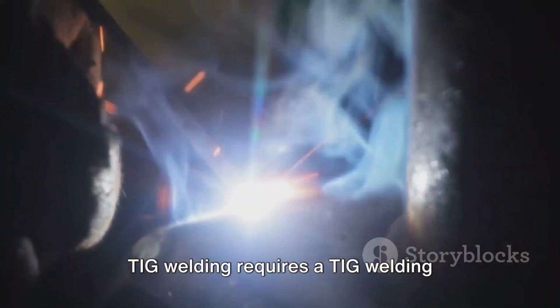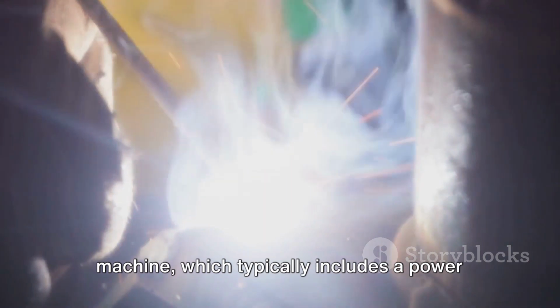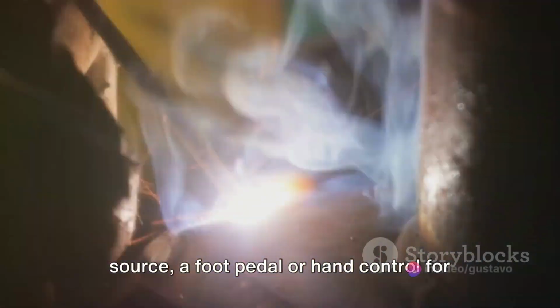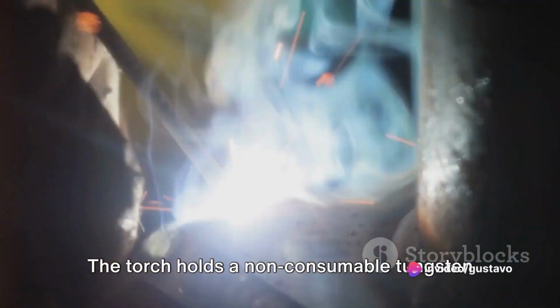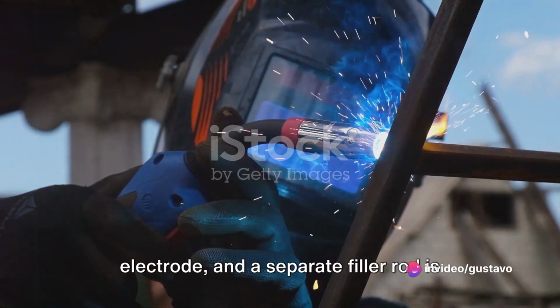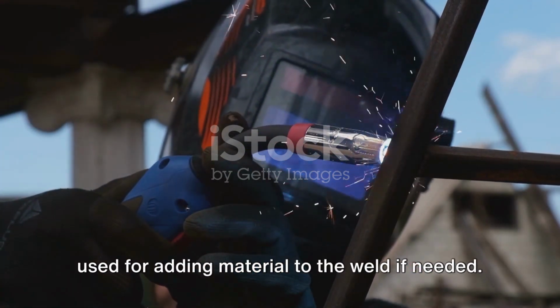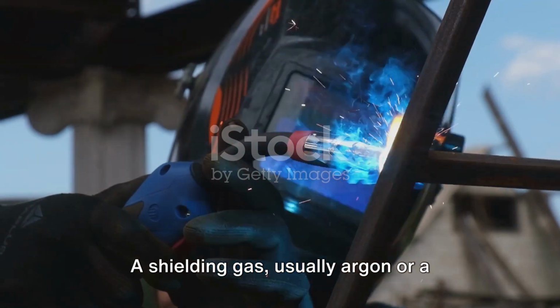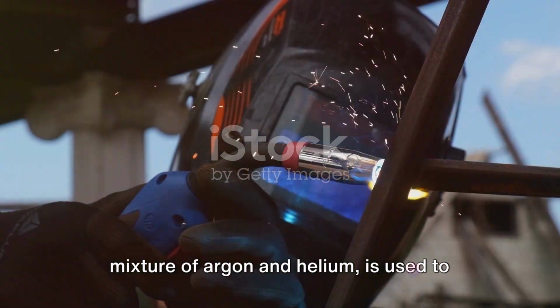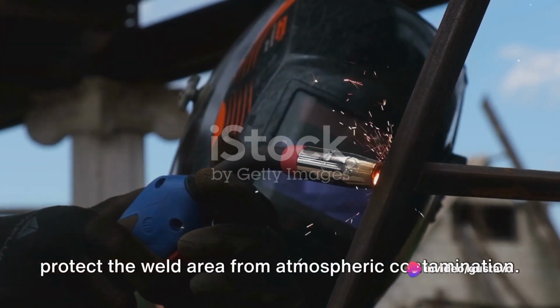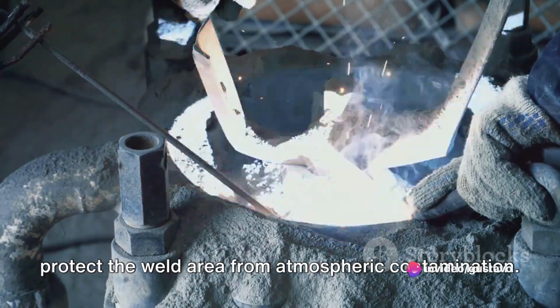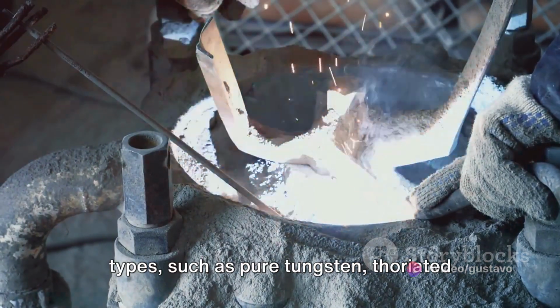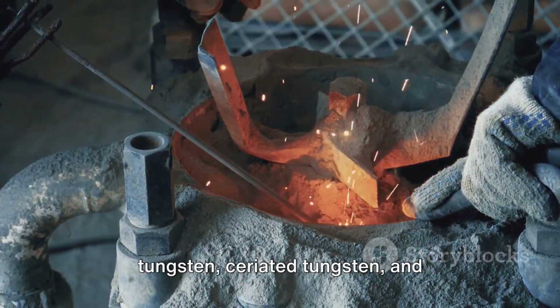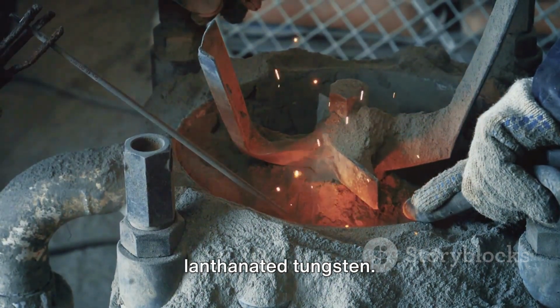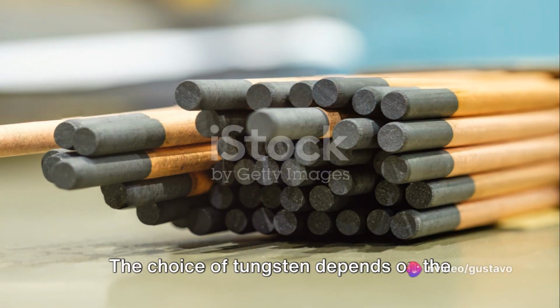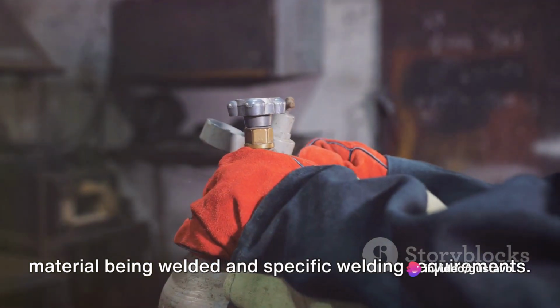TIG welding requires a TIG welding machine, which typically includes a power source, a foot pedal or hand control for amperage adjustment, and a TIG torch. The torch holds a non-consumable tungsten electrode, and a separate filler rod is used for adding material to the weld if needed. A shielding gas, usually argon or a mixture of argon and helium, is used to protect the weld area from atmospheric contamination. Tungsten electrodes come in various types, such as pure tungsten, thoriated tungsten, ceriated tungsten, and lanthanated tungsten. The choice of tungsten depends on the material being welded and specific welding requirements.